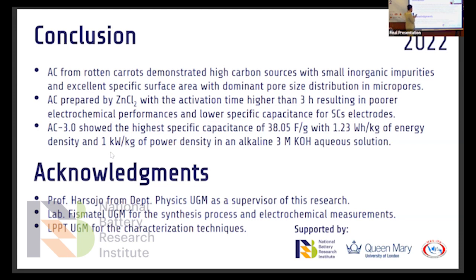Conclusion. Finally, from this research, we can conclude that activated carbon from rotten carrots was successfully made, and an activation time higher than 3 hours affects the particle size and pore distribution, in which the best electrochemical performance was achieved by AC3.